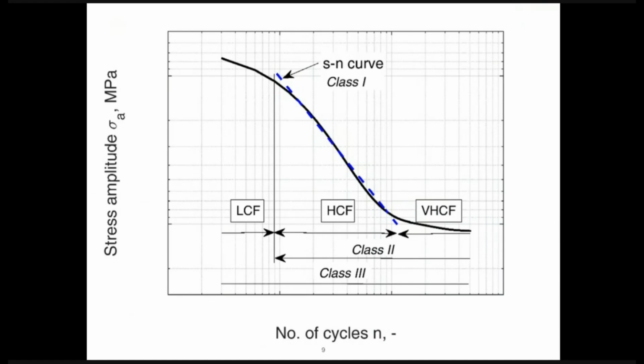So just a short reminder about the SN curves and the model we are going to use. We have low cycle fatigue, high cycle fatigue, and very high cycle fatigue. The tests we did were all in the regime of elastic stresses, so we did high cycle fatigue in this case, but the model is a class 2 model, so it can be applied to very high cycle fatigue, not so much to low cycle fatigue. But yeah, high cycle fatigue and very high cycle fatigue is what we can use the model for.